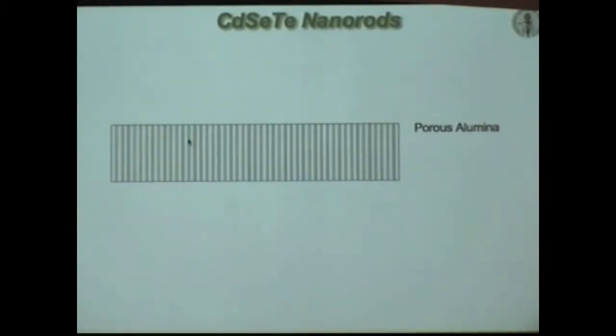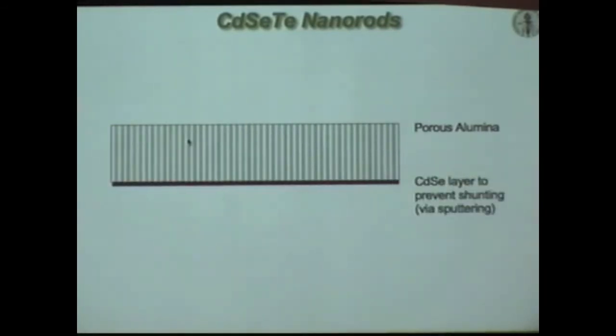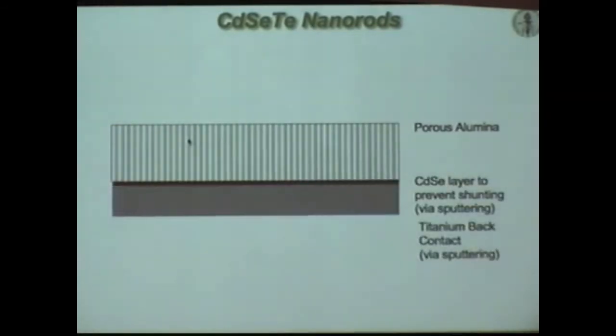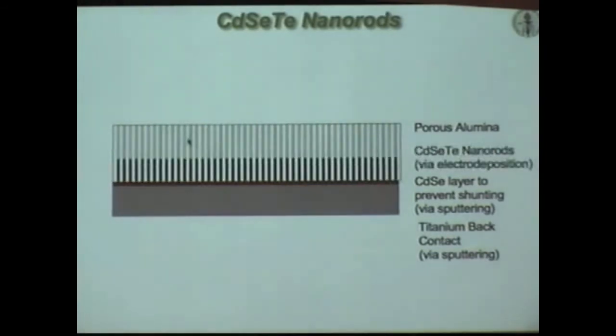It was just a prototypical material that we could test the theory on, because we know we can electrodeposit this. We know it's photoactive. We also know that you can't make it have a diffusion length longer than 1 micron, and you need 3 microns to absorb all the light. So in a bulk crystal or thin film, we know it's highly inefficient. So we just sputter a cadmium selenide layer there, put a metal back contact on, electrodeposit from a bath the cadmium selenide telluride in our template.